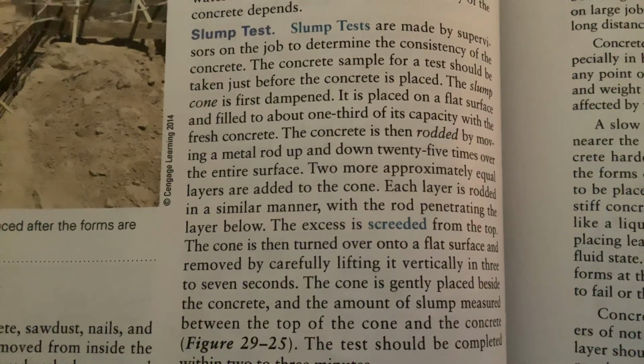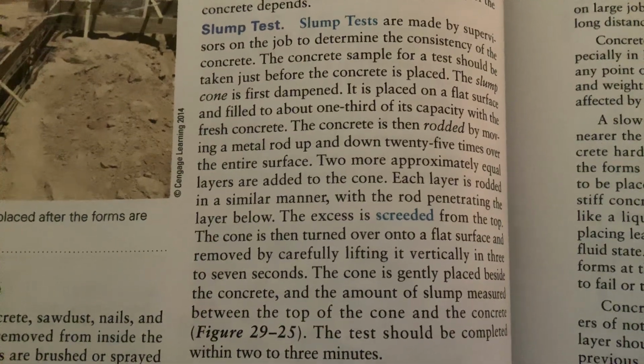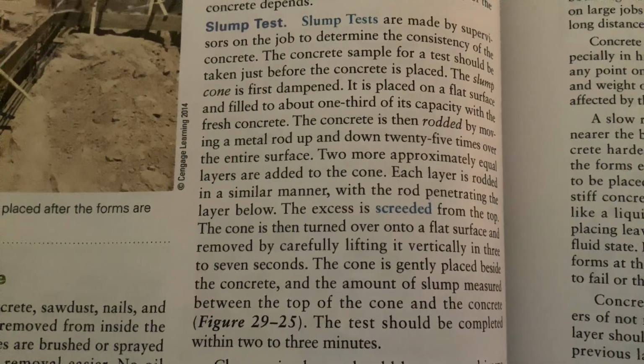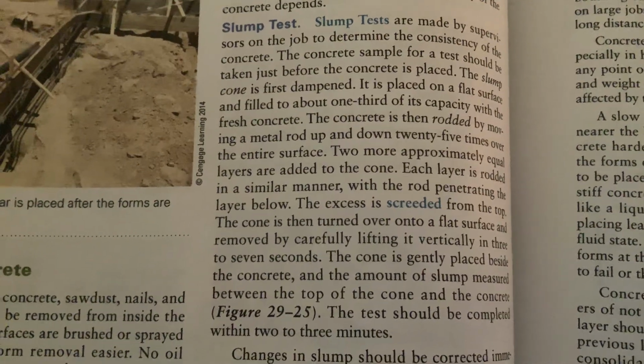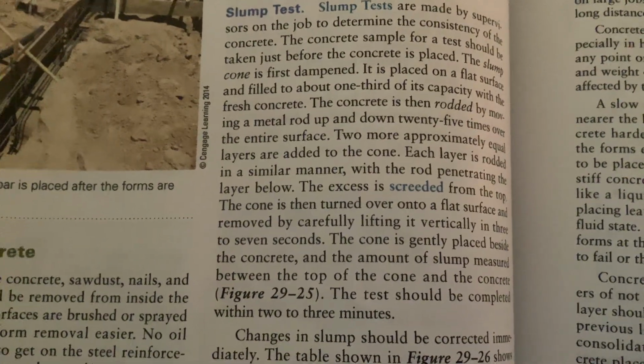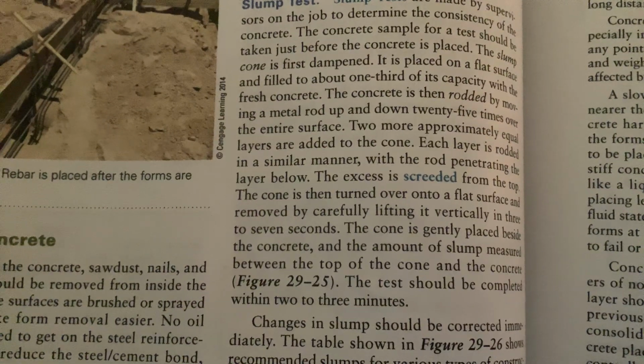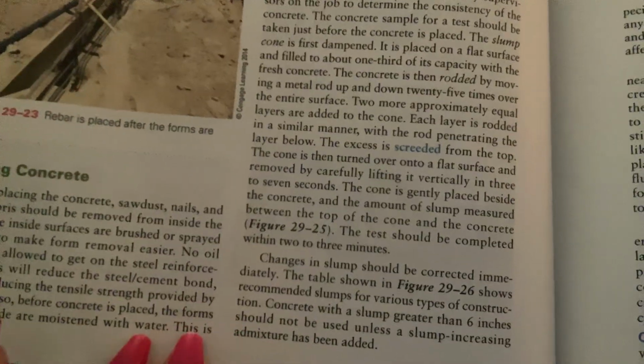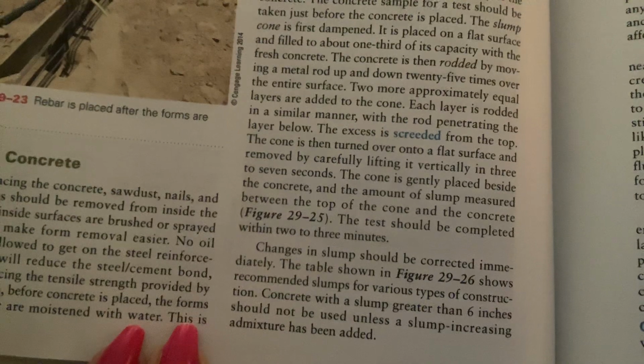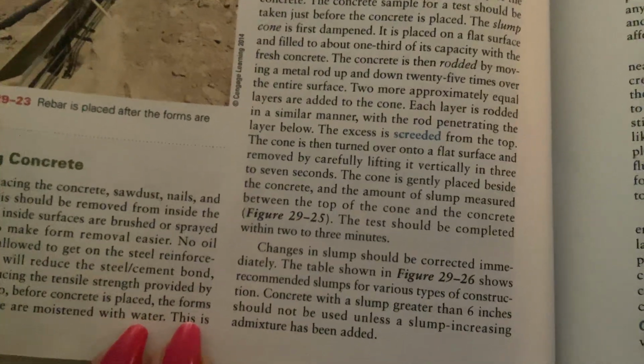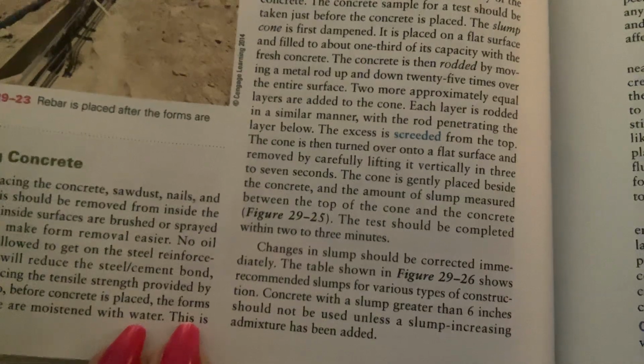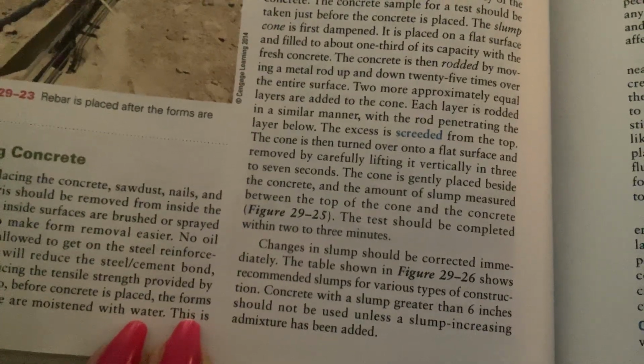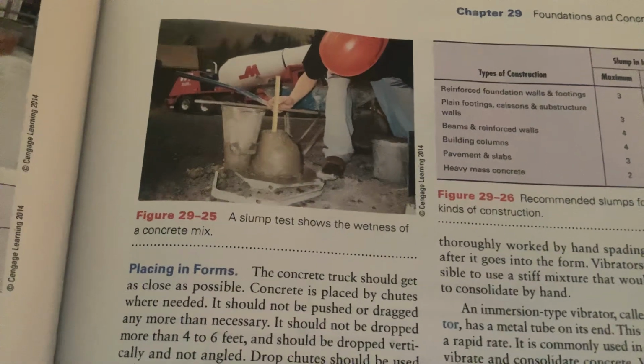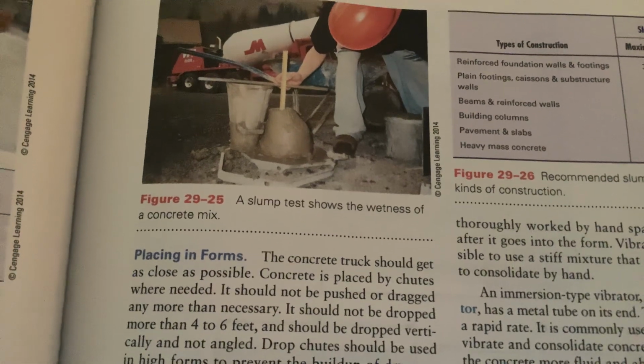The excess is screeded from the top, then the cone is turned over onto a flat surface and removed by carefully lifting it vertically in 3 to 7 seconds. The cone is gently placed beside the concrete and the amount of the slump is measured between the top of the cone and the concrete. The test should be completed within 2 or 3 minutes. Changes in slump should be corrected immediately. The table shown in Figure 29-26 recommends slumps for various types of concrete. Concrete with a slump greater than 6 inches should not be used unless slump-increasing admixtures have been added. A slump test shows the wetness of the concrete mix.